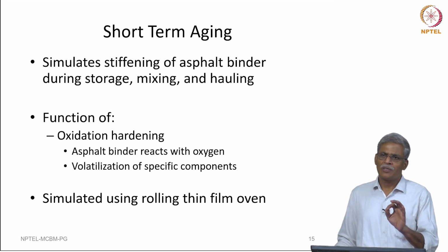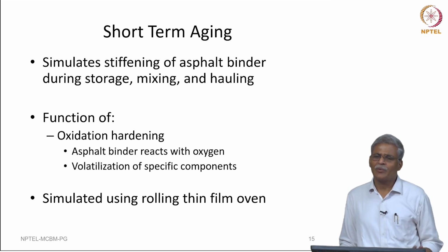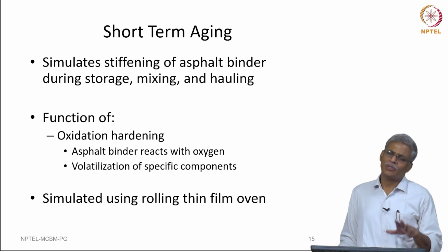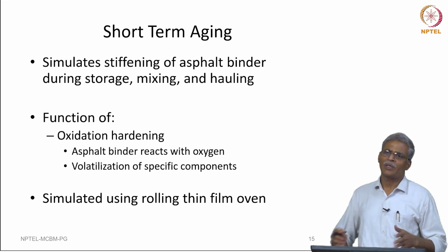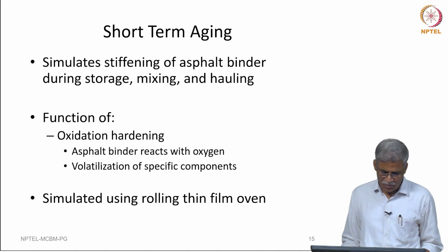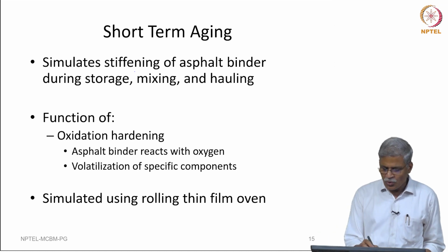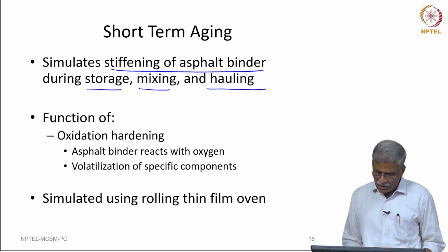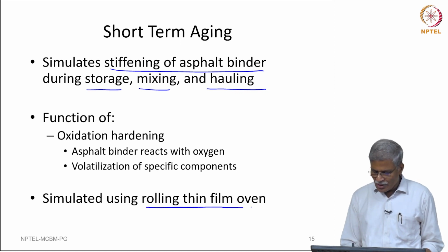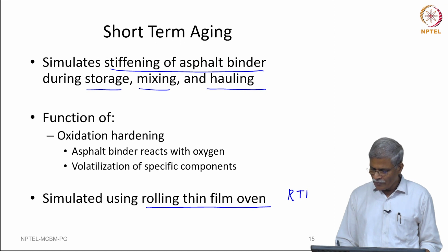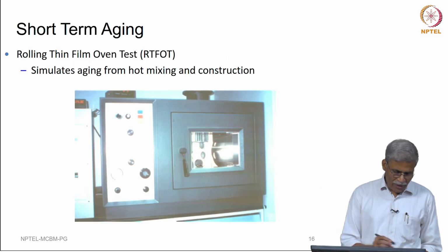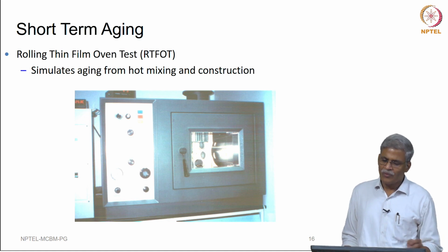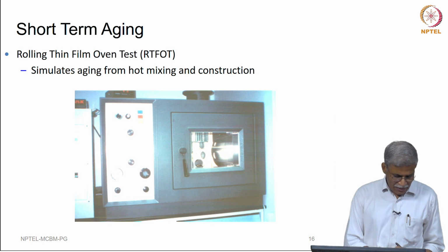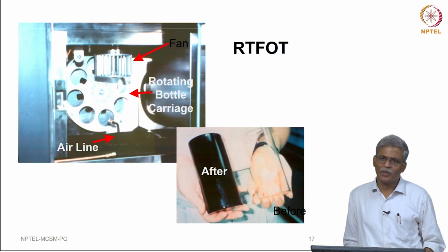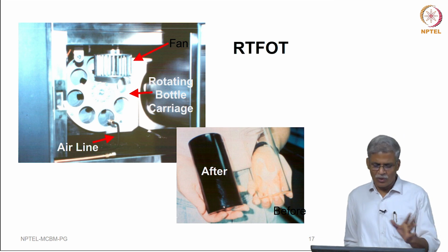So, now let us take a short detour here and talk a little bit about the short-term aging. The details associated with the short-term aging have already been discussed by Dr. Nivita when she talked about the aging of bituminous material. This will simulate the stiffening of the binder during storage, mixing and hauling, and we will be simulating it using what is called a rolling thin film oven, okay. A typical rolling thin film oven will look more or less like this, and these are representative pictures. Different rolling thin film ovens will look slightly different.